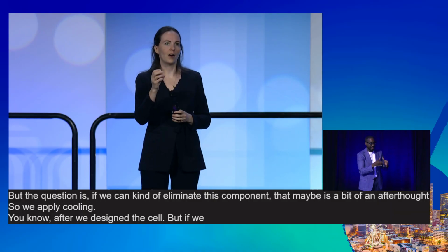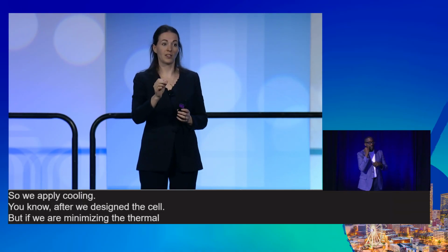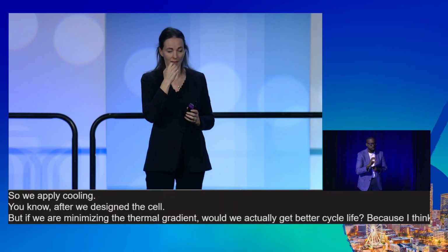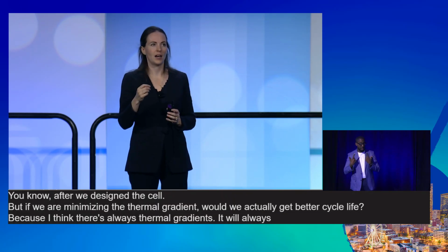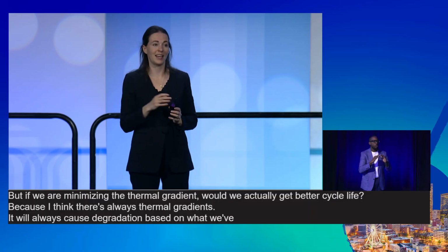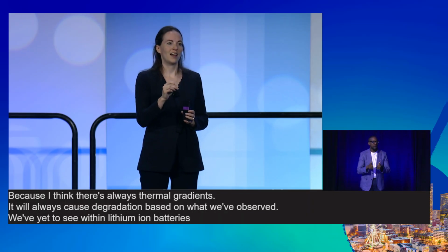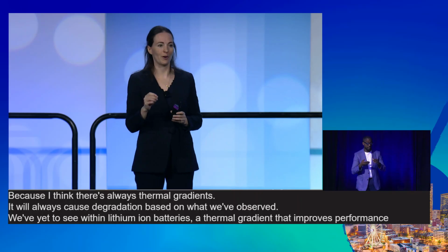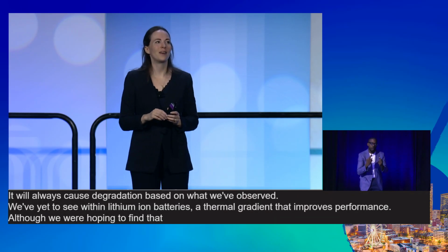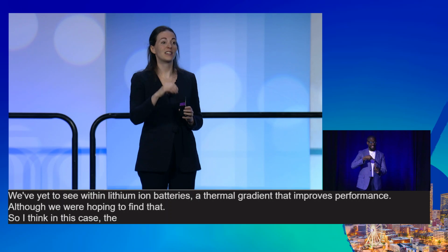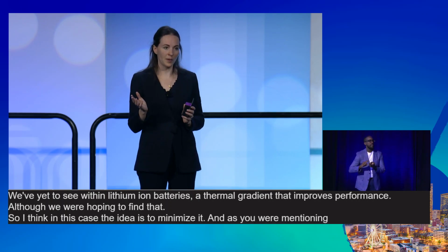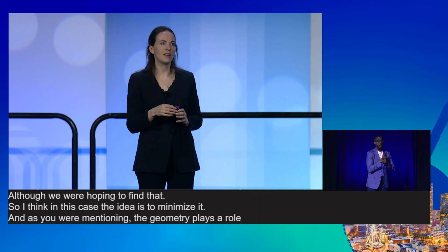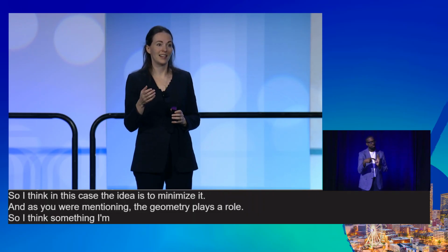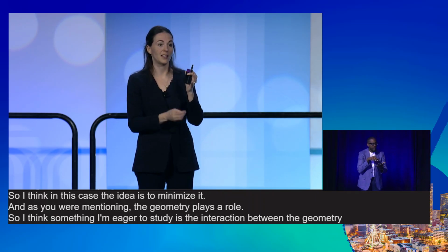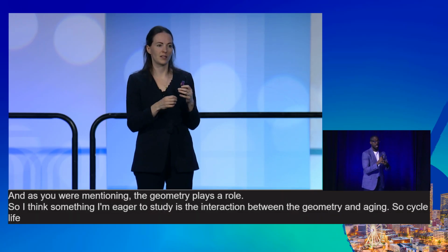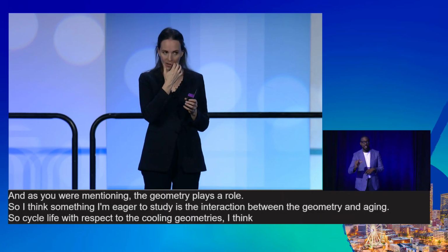But if we are minimizing the thermal gradient, would we actually get better cycle life? Because I think there are always thermal gradients. It will always cause degradation based on what we've observed. We've yet to see within lithium-ion batteries a thermal gradient that improves performance, although we were hoping to find that. So I think in this case, the idea is to minimize it. And as you were mentioning, the geometry plays a role. So I think something I'm eager to study is the interaction between the geometry and aging. So cycle life with respect to the cooling geometries. I don't think this has yet been investigated much.